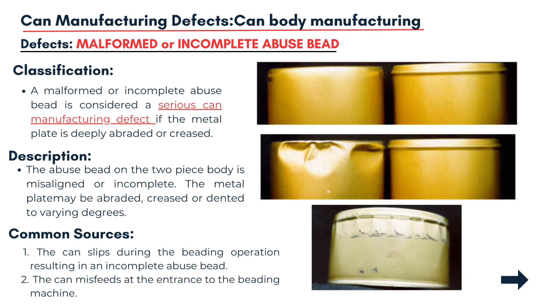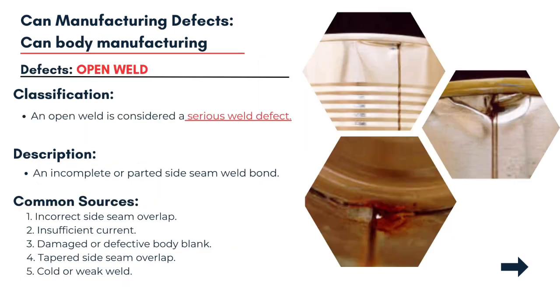This defect arises when the can slips during the beading operation, leading to an incomplete bead, or when the can misfeeds as it enters the beading machine. If the metal plate is deeply abraded or creased, this defect is classified as serious, compromising the can's structural integrity and potentially leading to failure. Another defect here is the open weld. It is a serious defect in can body manufacturing that occurs when the side seam weld bond is incomplete or parted. This defect is classified as a significant weld failure because it compromises the structural integrity and sealing capability of the can, which can lead to leakage, contamination, and ultimately product rejection or recall.